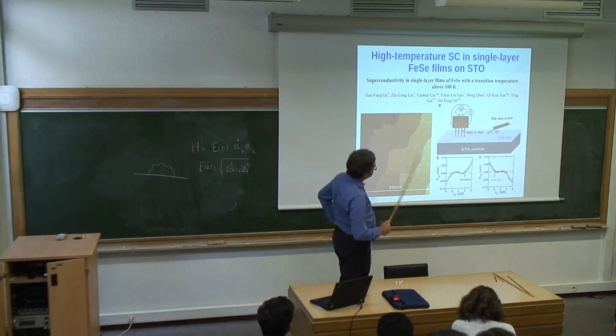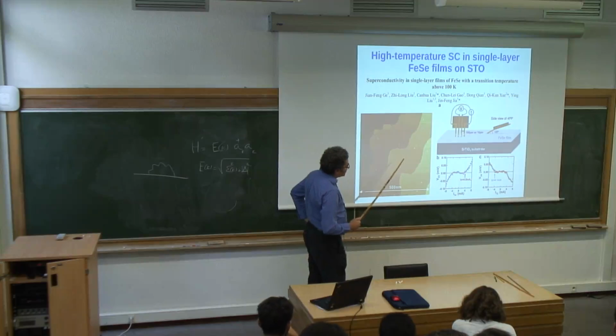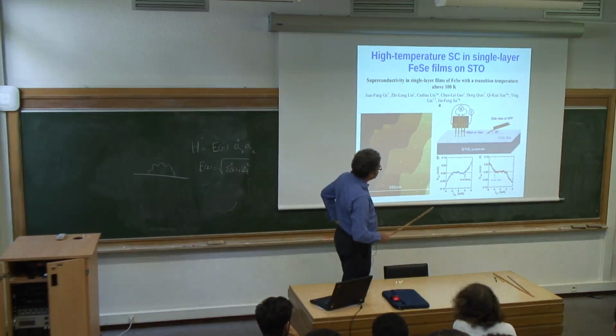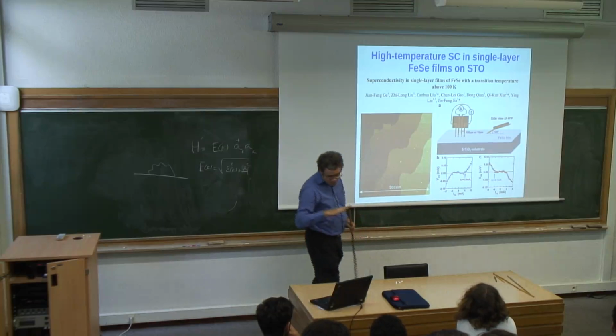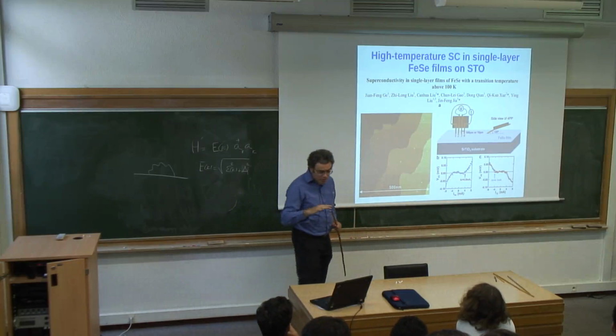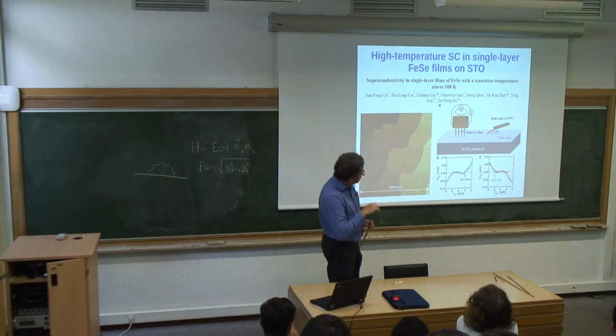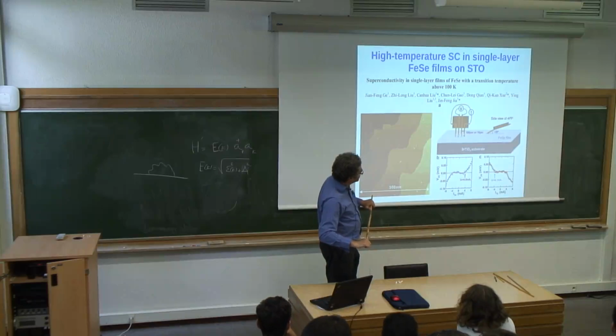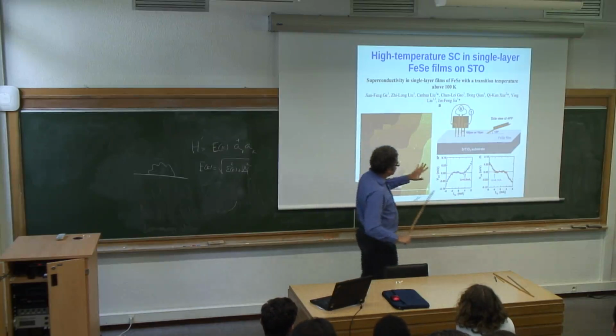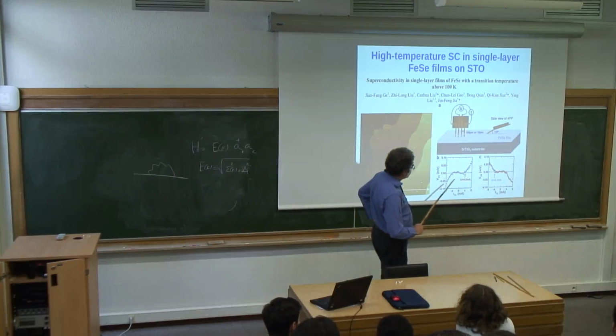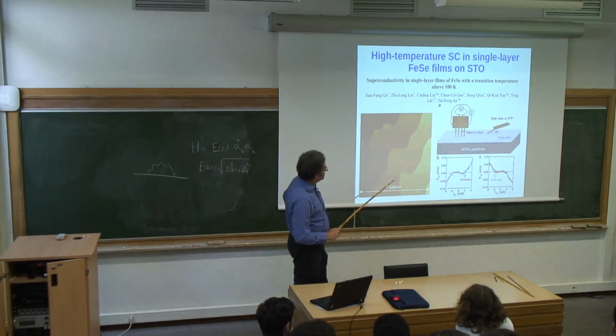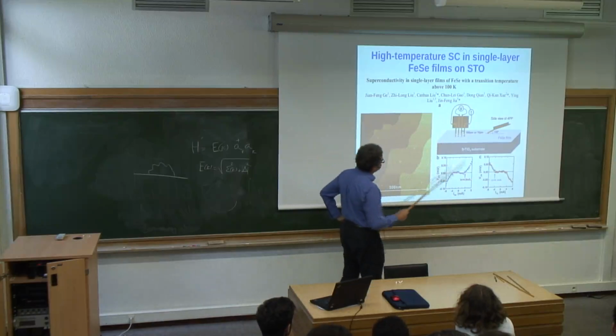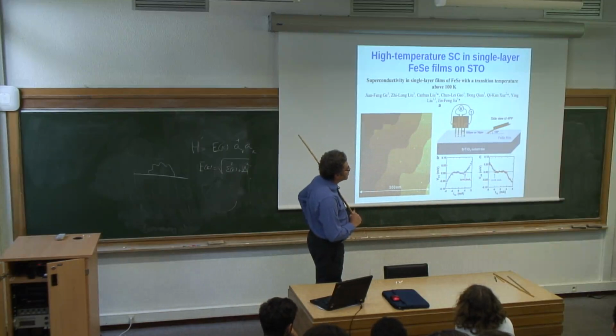it's superconducting up to 100 Kelvin at least, and perhaps even higher because, well, if you look at their data, it looks like their superconductivity is dominated by two-dimensional BKT fluctuation effects, and so 100 Kelvin is perhaps not the intrinsic value, but is the value after fluctuations suppress the intrinsic value down to a slightly lower value. In any case, they have critical current which is non-zero up to 110 Kelvin or so, and so this is potentially an example of what I've been talking about.